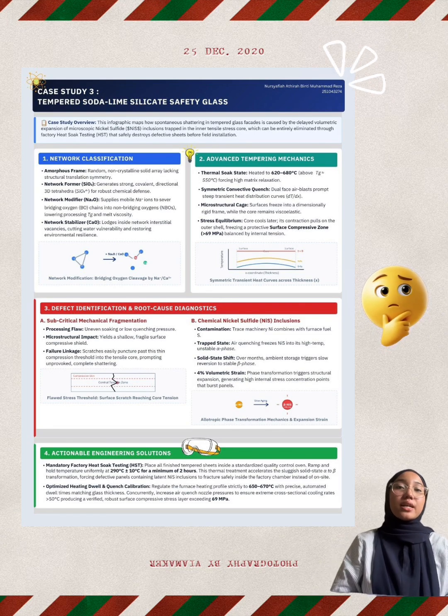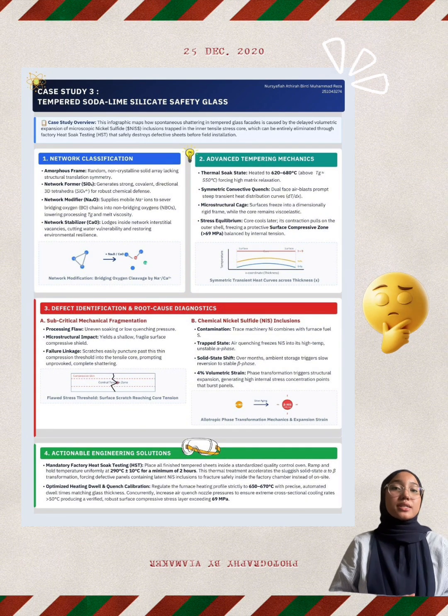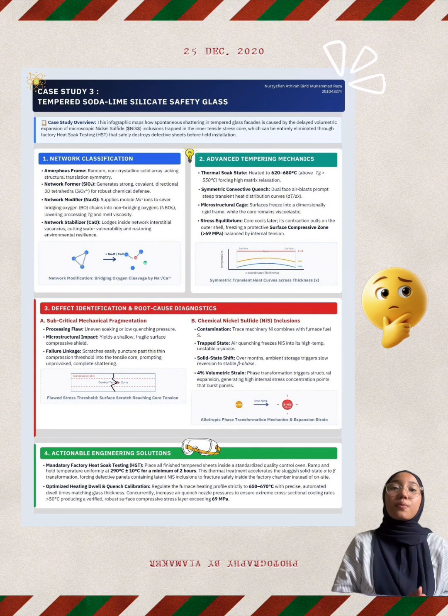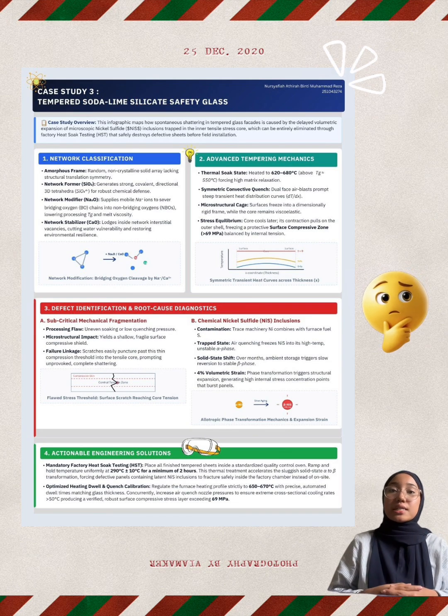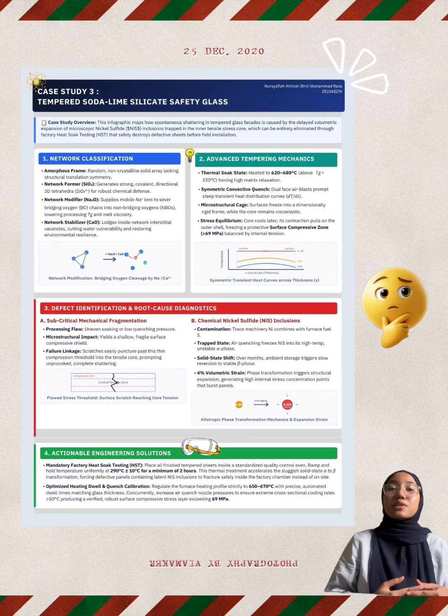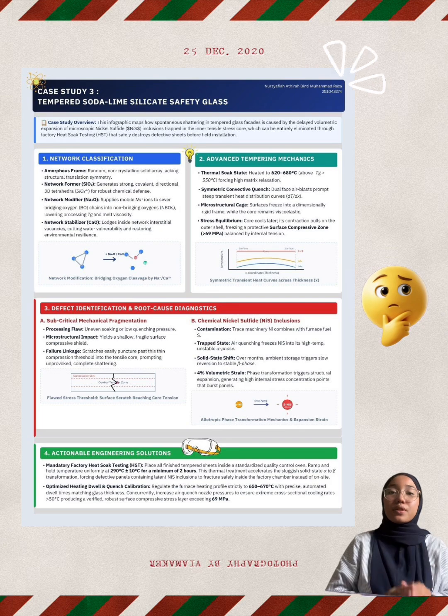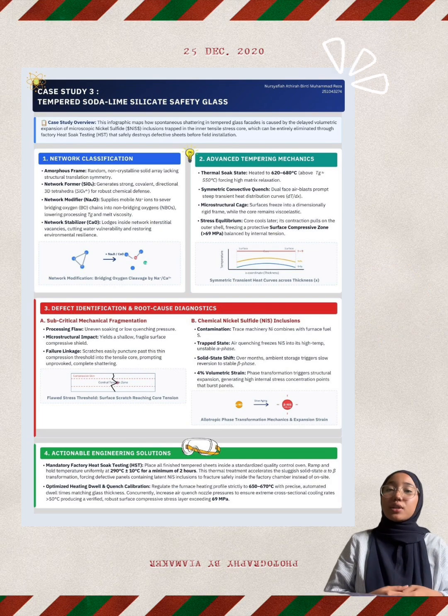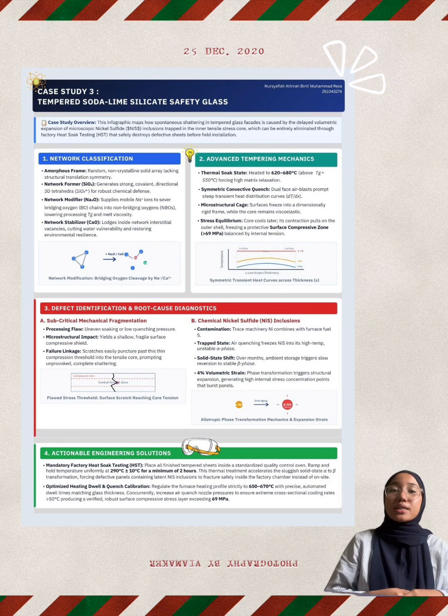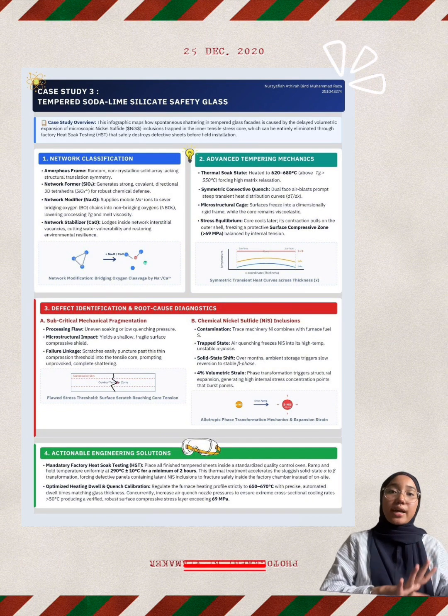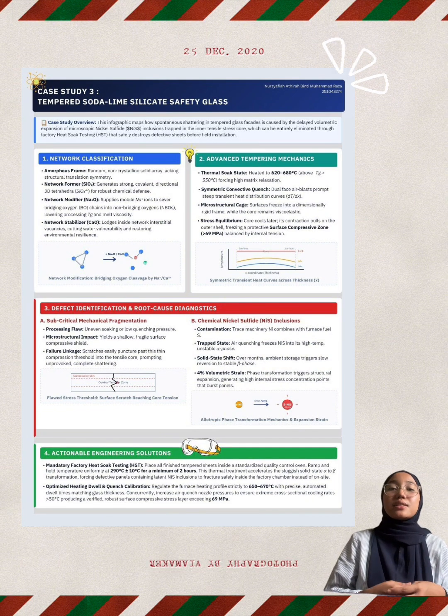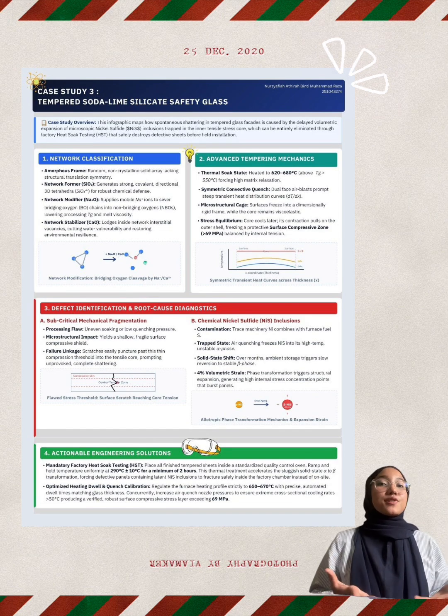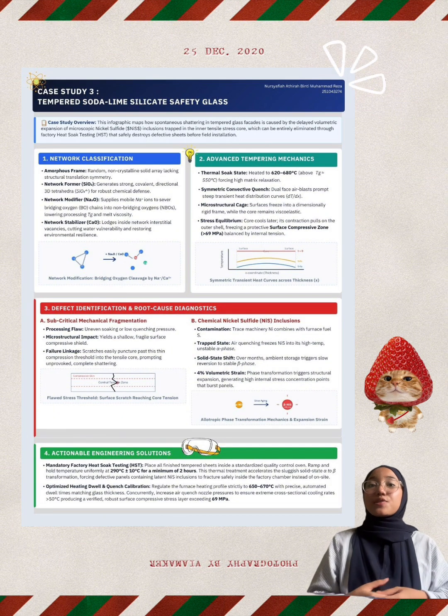Second, and more notoriously, are chemical nickel sulfide inclusions. This happens when trace nickel from machinery combines with sulfur from furnace fuel. The rapid air quenching process accidentally traps these microscopic inclusions in their unstable, high-temperature alpha phase. Over months of ambient storage on site, this inclusion slowly tries to revert back to its stable beta phase. This solid state shift triggers a massive 4% volumetric strain. As the particle expands in the glass core, it creates intense, localized stress concentration points until the entire panel spontaneously bursts.